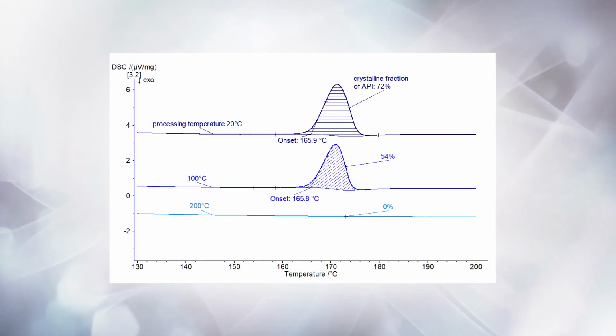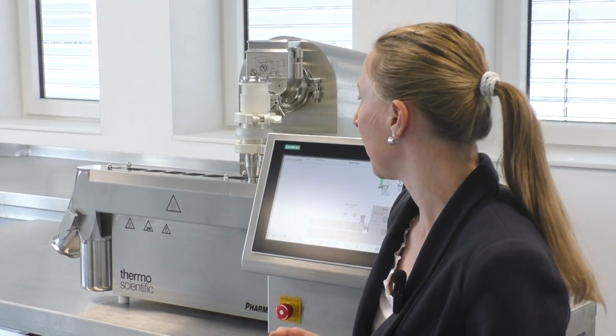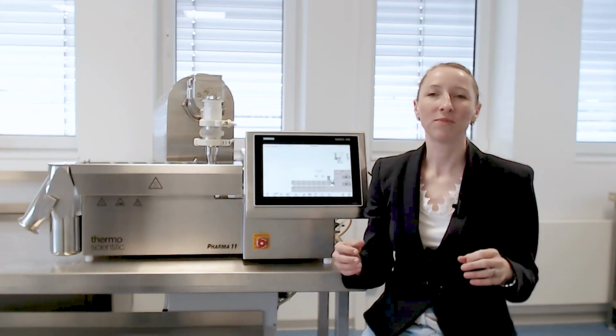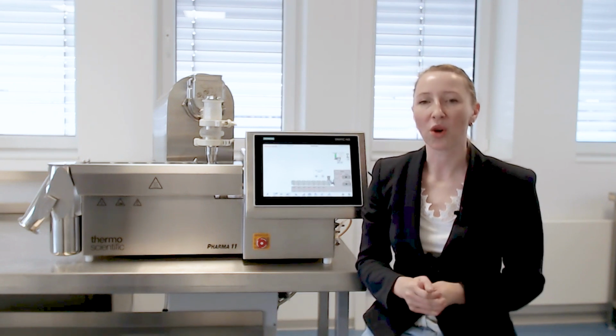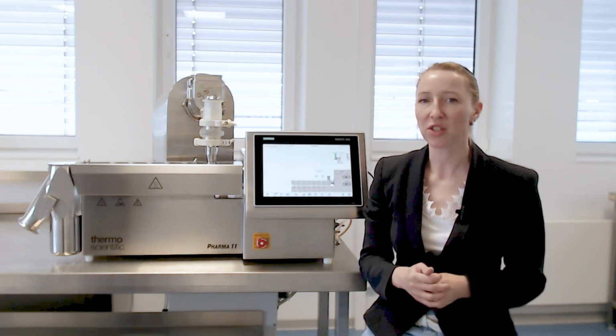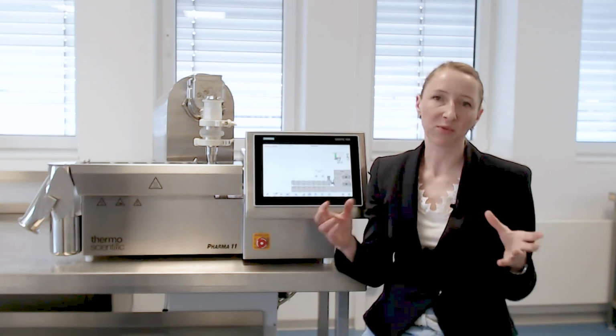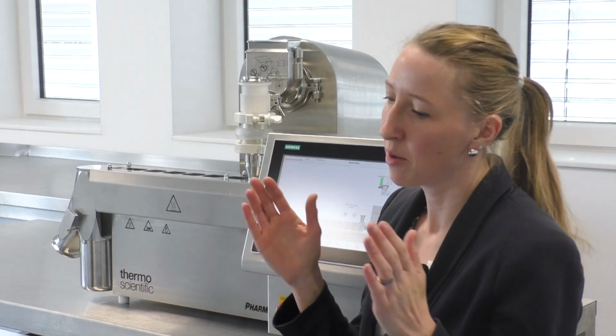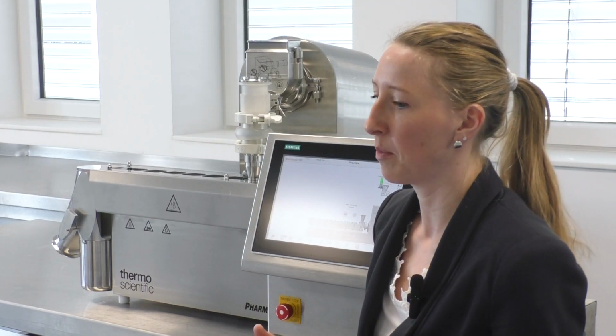That one helps you to identify a melting point, and if it's there, you can see, okay, we still have a crystalline state there. So DSC was one analysis we did. Another possibility is to work with X-ray diffraction, and with this we could very nicely see, do we still have crystalline parts in there?